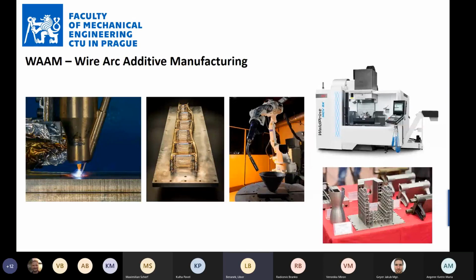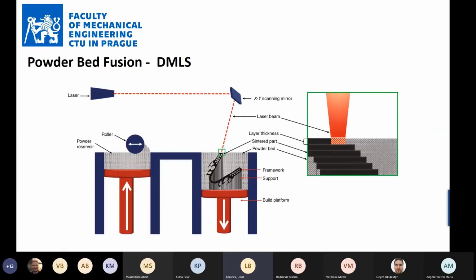So, regarding the principles of different technologies, maybe I can skip those a little bit faster. When I was speaking about wire arc additive manufacturing, just to figure it out, this can be a very cheap technology because robots are today quite accessible. MIG welding sources are again quite accessible, and their deposition rate is really within kilograms per hour. So with appropriate control over this machine, you can have quite large printing volumes, and you can print with, for example, argon atmosphere. You can even print titanium. So this is a titanium printout using the WAAM technology. Powder bed fusion, we have already discussed.